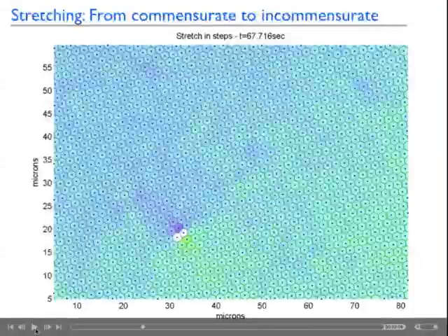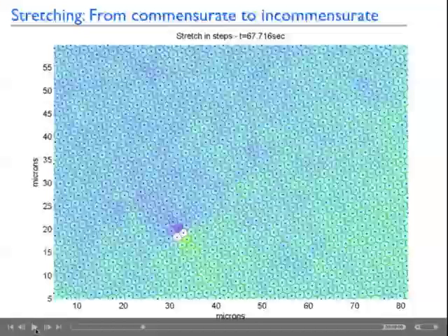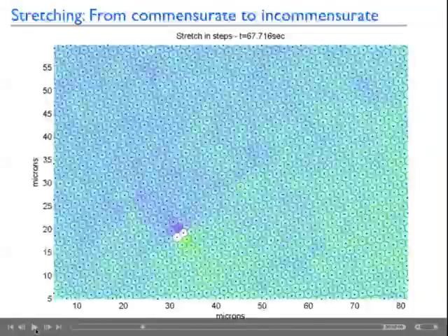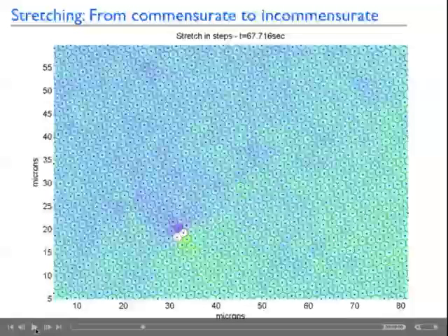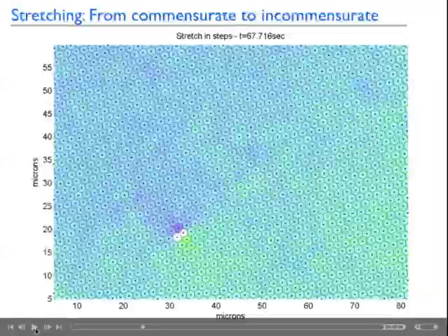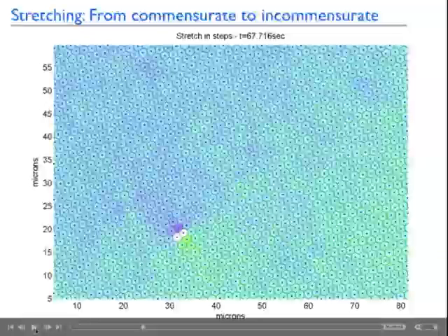Now, if you take a perfect lattice and you put a disordered potential on it, the lattice is going to distort, okay? And if the lattice is free to move, the whole lattice can move as a whole. If there's no potential on it, it's translationally invariant. But if I put disorder in, I can pin the lattice in different regimes. And this is a very important phenomenon, and it's known in charge density wave systems and charge systems like that as Lee-Rice domains, that Rice, okay? And in superconductors, it's known by something else. In that case, you have a vortex lattice, and you pin the vortex lattice. And there it's known as Larkin domains, or Larkin-Ovchinnikov domains, right?